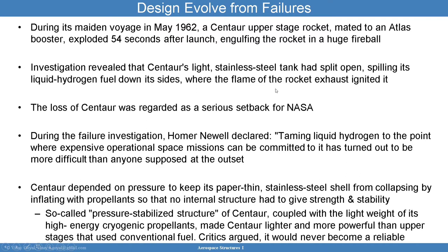So designs really evolve from failures. Anytime a launch vehicle experiences an anomaly or a spacecraft, it's an opportunity that we have for learning. And that was the case with the Centaur upper stage rocket during its maiden voyage in May 1962. It exploded 54 seconds after launch and engulfed the rocket into a huge fireball. And the investigation at the time revealed that Centaur's light stainless steel tank had split open and it spilled its liquid hydrogen fuel down its sides, where the flame of the rocket exhaust ignited it.